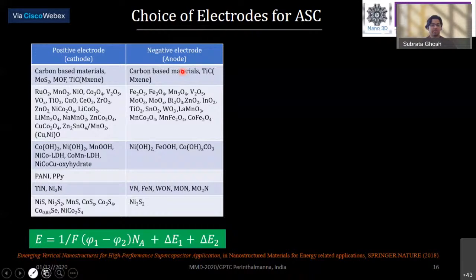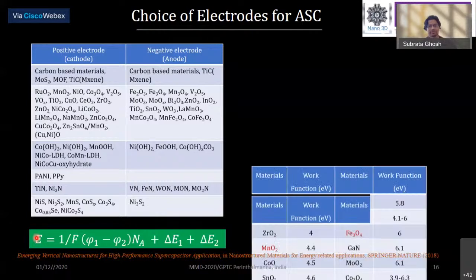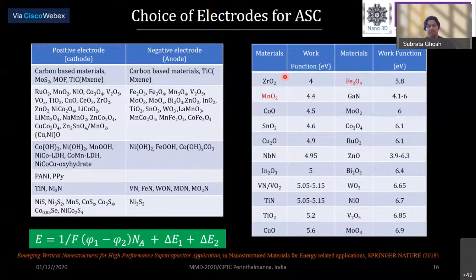As I mentioned, this potential window E also depends on the work function. This phi1 and phi2 are the work functions of the electrode materials. Because of the work function difference between the electrodes, you have delta E1 and delta E2 from the positive and negative electrodes, and as a result you can get a potential window of more than 2 volt. I will show one of my results. In the material list, I have listed the work functions: zirconium oxide is 4, and molybdenum oxide is 6.9.